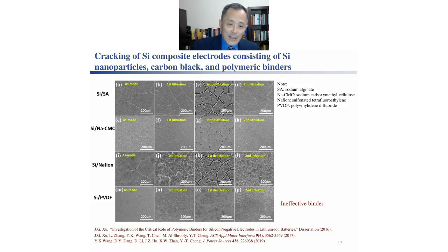On this slide are images of silicon composite electrodes made of different types of polymers as binders, for example, PVDF, Nafion, and sodium alginate. Quite surprisingly, as you can see, cracking can occur in the electrodes. Quite surprisingly, the one that does not have many cracks, such as in the case of using PVDF as a binder, is a very ineffective binder for silicon electrodes in terms of the cycle life of the electrode.